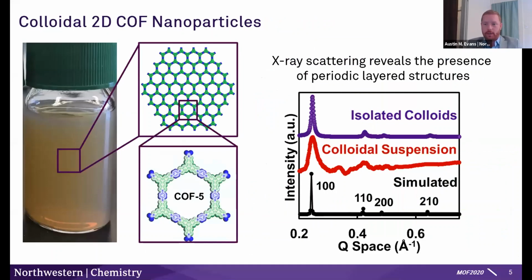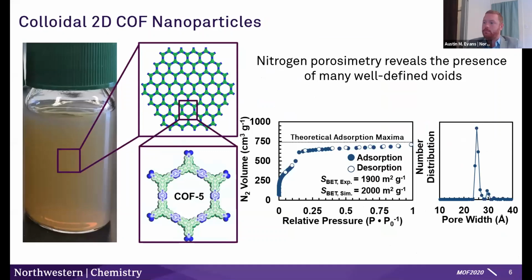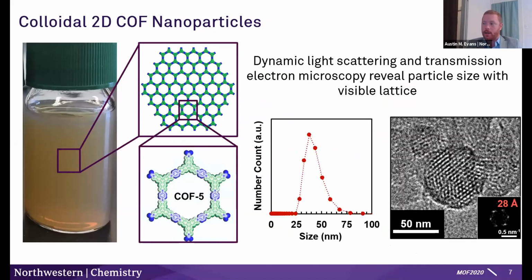And we can do all of the standard characterization we do on polycrystalline aggregates, which I'm sure you're all familiar with. You can look at the X-ray diffraction pattern and see the expected peaks. We can isolate these colloids via centrifugation and check their surface area. They have very conventional type 4 isotherms with high surface areas and sharp pore size distributions. And we can look at the particle size in situ using techniques like dynamic light scattering, or ex situ using things like TEM. And in both cases, you'll find that the domain size is about 50 nanometers.